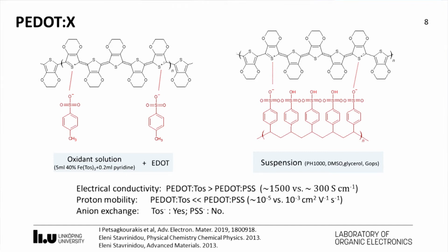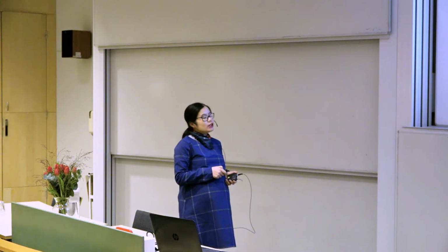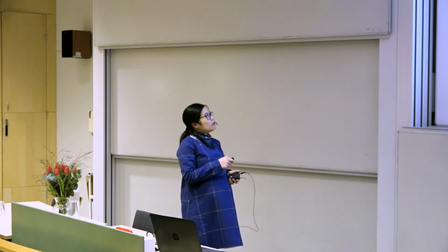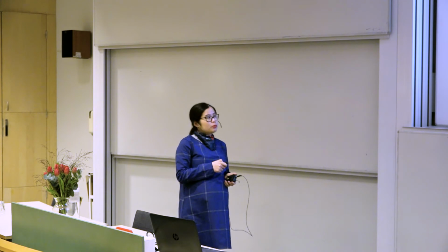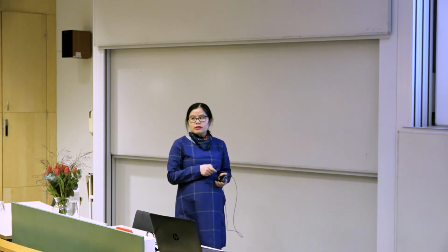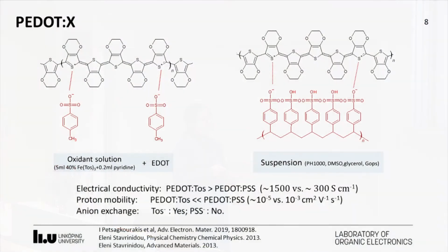The resulting conducting polymer PEDOT:TOS shows higher electrical conductivity in comparison with PEDOT:PSS due to higher crystallinity and also higher thiophene to sulfonate ratios. But PEDOT:PSS presents higher proton mobility compared to PEDOT:TOS due to the protons in the PSS. Besides that, due to the smaller size of tosylate ions, tosylate is a mobile counter ion during the charge and discharge process and can be exchanged by other small counter ions, small anions, while PSS is a polyanion, and especially